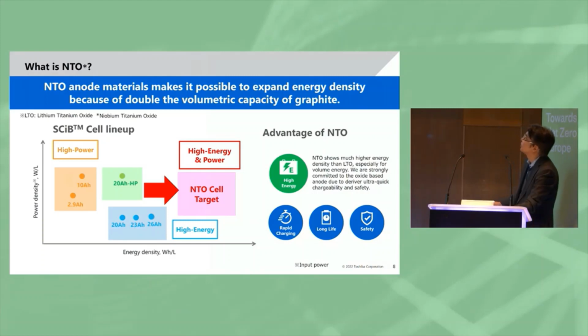The next point is fast charging. The fast charging performance is one of the main characteristics of the LTO batteries, and the NTO battery can inherit that performance. The reason is the difference in the reaction potential. NTO's reaction potential is close to the LTO, and it's much nobler than that of the carbon graphite and the lithium metal reaction. So the potential gap protects the anode from lithium dendrite deposition in charging situations, especially fast charging and low temperature charging. So the battery using the NTO anode can show high energy density and fast charge acceptance.